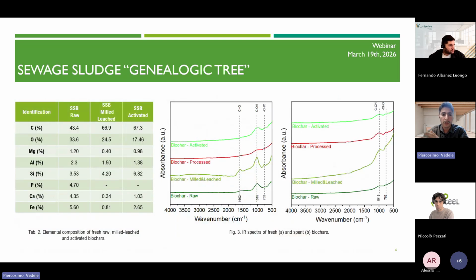As you can see, the different upgrading processes conducted on the char allow us to obtain a different composition of the material. By increasing the upgrading, we are increasing the gravimetric percentage of carbon and reducing the amount of oxygen of our char, and at the same time also reducing the inert part of the char. This is explained by the elemental composition that you can see in the table on the left, and is reflected also by the IR spectra of the biochar. As you can see from the spectra, we have a reduction of the peaks mainly related to carboxylic and hydroxylic functional groups, which present oxygen.